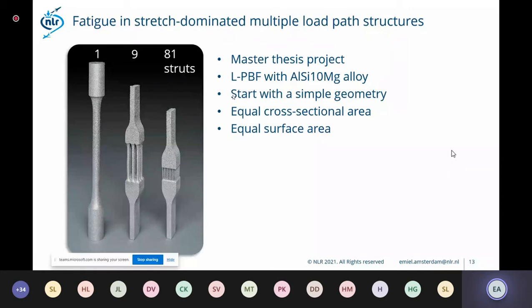For this example, we looked at 3 different specimen geometries: one with a single strut, one specimen with 9 struts in parallel, and one with 81 struts in parallel. They all have an equal cross-sectional area, so the force is the same. That's what we want to investigate: how good is the structure in maintaining that force over a long period of cycles? They also have equal surface area.